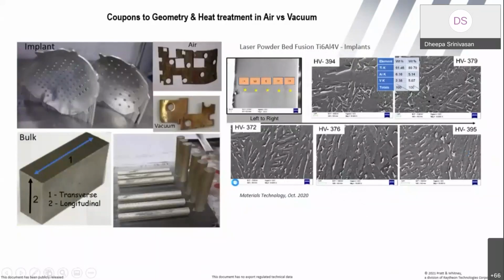We just looked at the effect of the microstructure here between the edge and the center of the thin wall implant structure. There could be variability in the microstructure because, as you know, in Ti-6-4, the pickup of oxygen at the edges is more, especially in thin sections like this. And once the oxygen gets picked up, there is a change in the alpha beta titanium structure along the edge. So that is another challenge. I'm not going into the details of it. You can find it in this publication. But that's a bigger challenge to also look at.